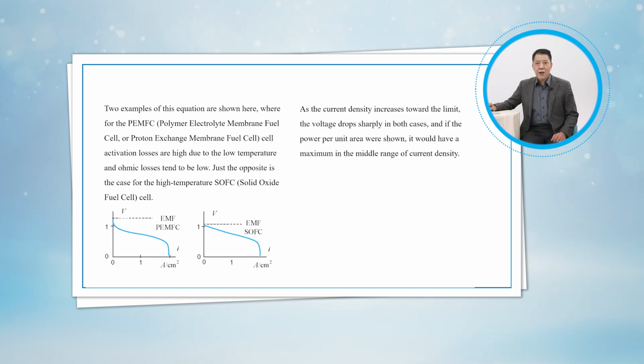Two examples of equation 14.7 are shown here, where for the PEMFC cell, activation losses are high due to the low temperature and ohmic losses tend to be low. Just the opposite is the case for the high temperature SOFC cell. As the current density increases toward the limit, the voltage drops sharply in both cases, and if the power per unit area were shown, it would have a maximum in the middle range of current density.